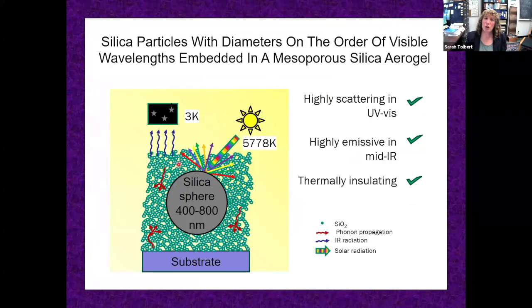And so what we want to create is silica glass in a porous network so that it can strongly emit IR light. And then we're going to embed in it big spheres of silica glass where the size is picked to scatter all of the incoming sunlight. And so our goal is to scatter away the sunlight and then emit heat to the vacuum of space. So this is our cartoon. It's all glass, silica, a porous network, and big scattery spheres.